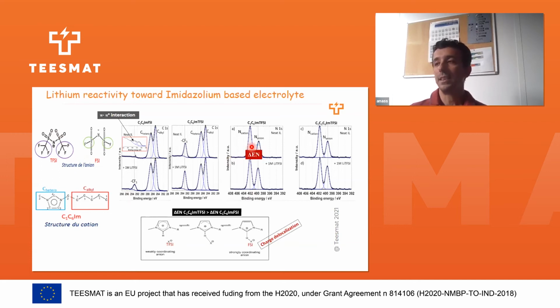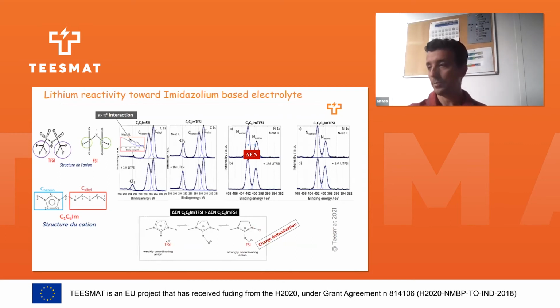What is interesting is that the chemical shift, or the energy difference between both peaks, can be related to the interaction between anion and cation. We could build some model here depending on the delta, the difference between cation and anion energy, and we can link that to the interaction, the coordination between anion and cation. The weaker the coordination, the higher the delta. So that also can give some information about charge delocalization in this system.